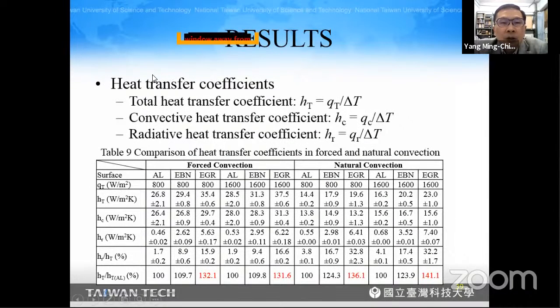So now we summarize all the experiments in this table, and the total heat transfer, there are heat transfer coefficients, and they are calculated according to this equation. And we can see the result using the bare aluminum plate as the base for comparison. For forced convection with the green graphene loaded coating, the ratio of total heat transfer versus aluminum heat transfer increased to 132.1. That is 30% of increase improvement in the heat transfer.